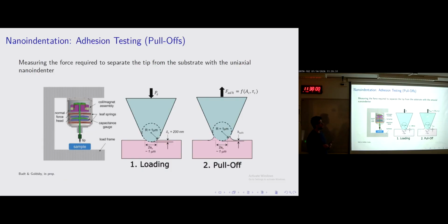The adhesion is dependent on the contact area, obviously, and the bonding that occurs between these two solids. It's still diamond. Well, yes, but we'll go back into that in a bit. The thing is that this is a very simple stress field. We're just pulling on it. So there's no shear that complicates things and makes it a bit harder to interpret. And also, contact area during the pull-off doesn't really grow. It can only decrease, right? So contact area growth is disconnected from this process. So we can really look into the contact strength.